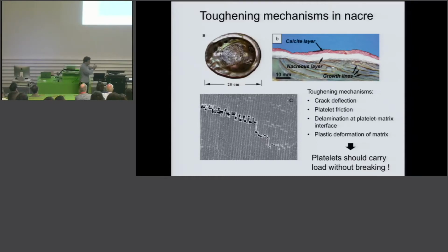Crack deflection, friction of the platelet as you try to pull it out of this surrounding material, delamination between the platelet and this organic phase, which we call matrix here, plastic deformation, and so on. But all these require that the platelets do not break. So the platelets should carry as much load as possible, but should not break. They should carry a lot of load because they are the stiff phase, and what connects the individual platelets to the outside world is this 5% organic phase in between, right? So they should carry as much load as possible, but should not break.